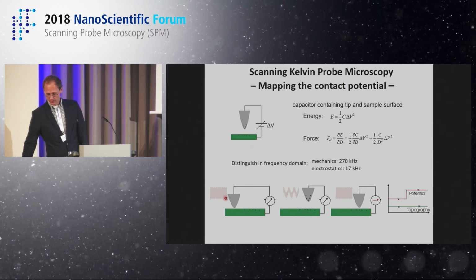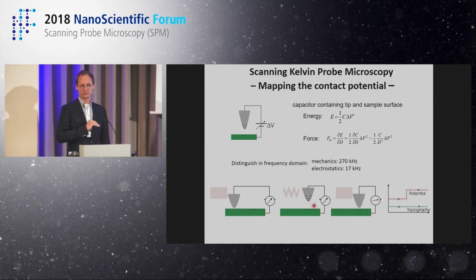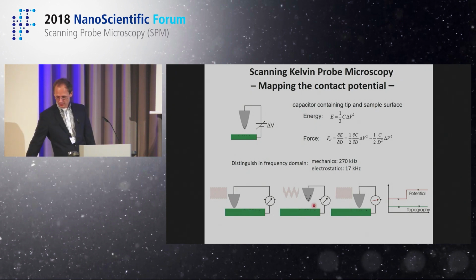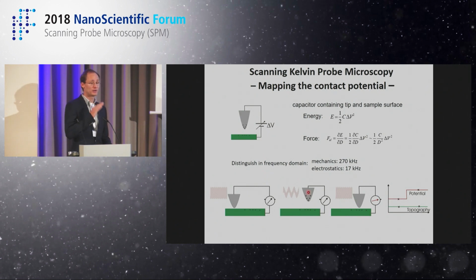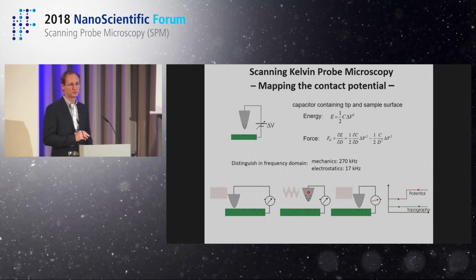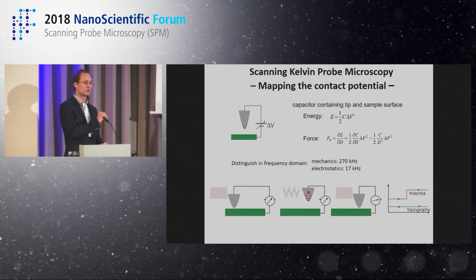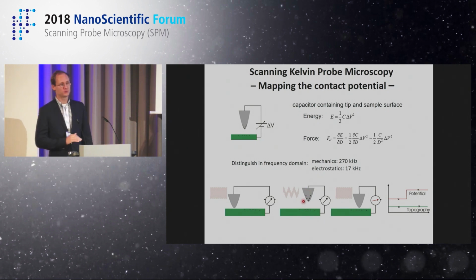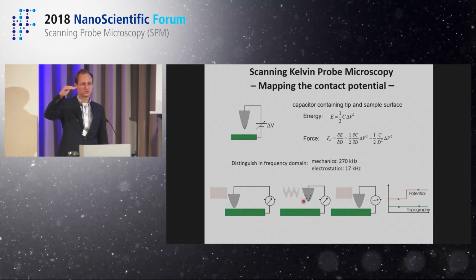Now we scan our surface and we get to an area where we have an electrostatic interaction. Let's say there are, for example, some charges trapped in the surface. There is a different metal. What happens is, due to this Kelvin effect, we get kind of a charging of our tip. We have this additional attractive electrostatic interaction. If we just think about our non-contact experiment, this would lead to a shift of our resonance curve, the amplitude would go down, the feedback system would activate and just pull our tip apart from the surface. So it would look as if there is a step in surface height, right? An artifact due to electrostatic forces.